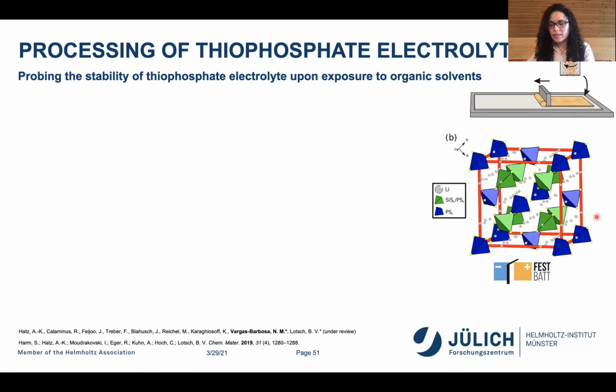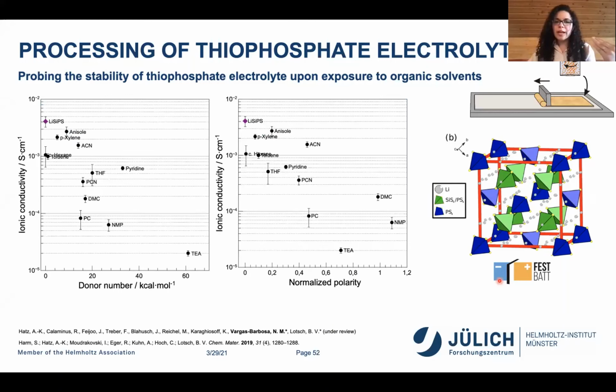The Lotsch group has tetragonal lithium silicon thiophosphate, which is in the family of the LGPS-type solid electrolytes. As a starting point, it has about 1 to 2 millisiemens per centimeter room temperature conductivity, so it's quite competitive. We looked at what happens when it's exposed to a solvent. The reality is that we start somewhere up here, and upon exposure to any kind of solvent, we tested about 12 or 15, the conductivity always drops.